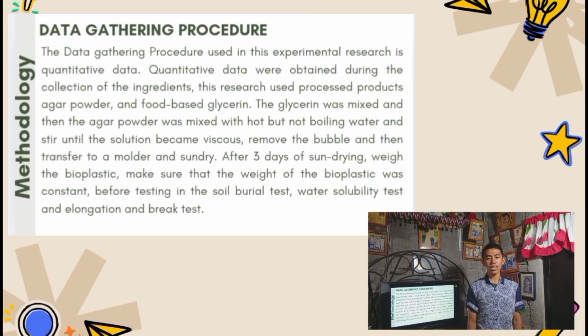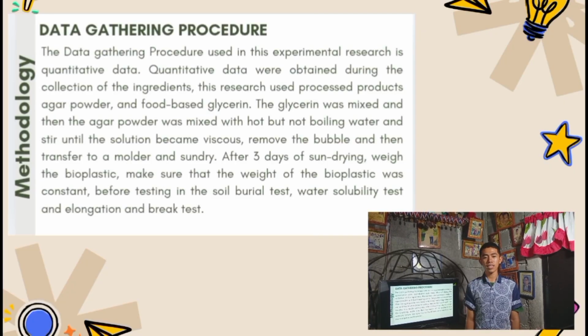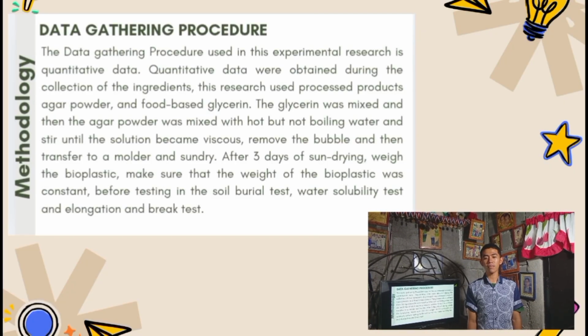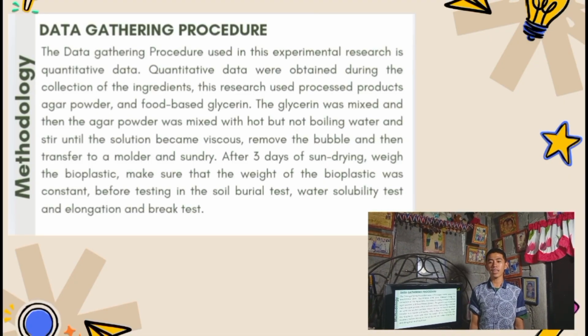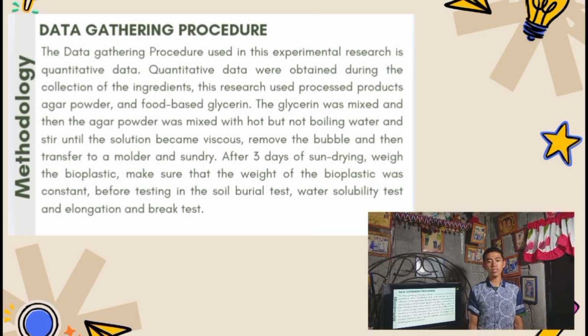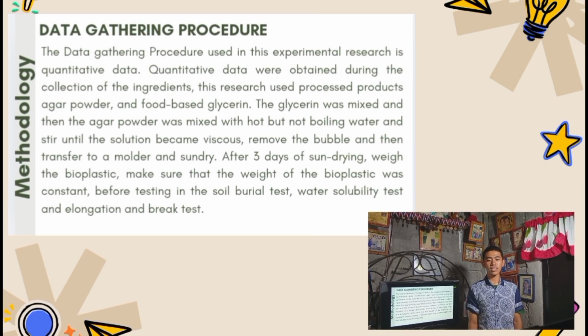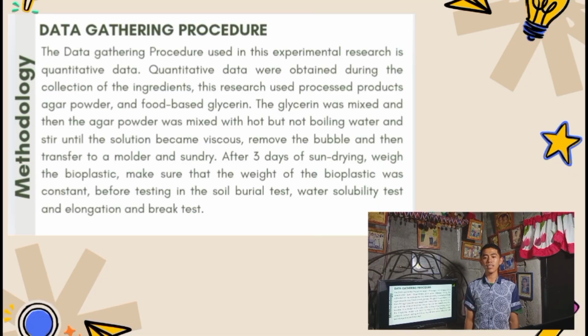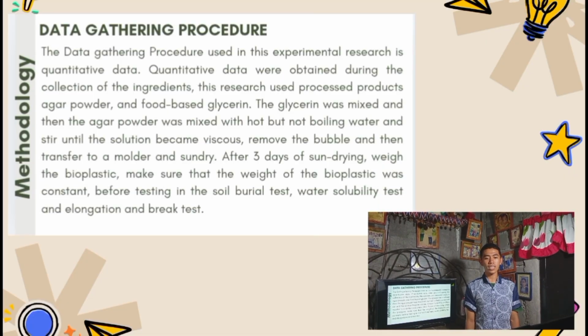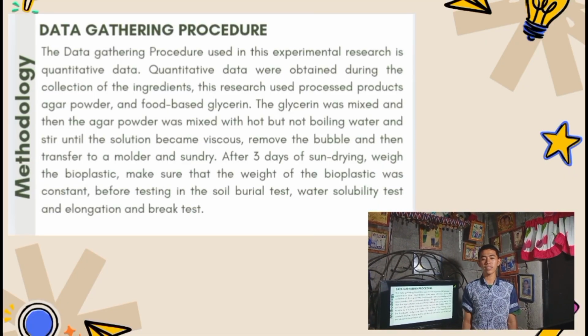Agar powder and food-grade glycerin are gathered as primary ingredients. Glycerin is combined with agar powder in hot but not boiling water. The mixture is stirred until it reaches a specific viscosity, and air bubbles are removed to ensure structural integrity. The solution is cast into a mold and sun-dried for 3 days until the weight remains constant.